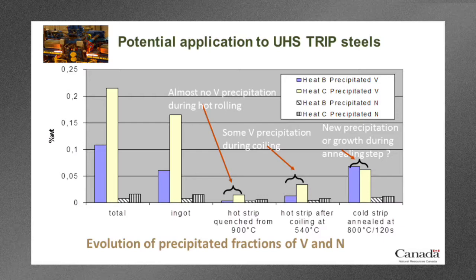Now, in the as-cast ingot, what we found was that of that 0.1 weight percent, we had just over half that was precipitated in the ingot itself. Then that ingot was reheated and hot rolled, and we quenched it after hot rolling from 900 degrees C. Now, vanadium is very soluble in austenite, and what you can see in the diagram is that all of the vanadium's gone into solid solution. There's very little precipitated at that point. Very interesting property that vanadium has, because it means that we're not doing anything really to the hot strip microstructure. We're not strengthening the hot strip microstructure, so we're not going to be loading our hot strip mills, for example, and that can be one of the problems with these high strength steels. So vanadium is very good for that.